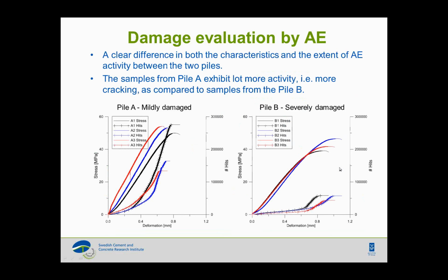This is just some results from acoustic emission for pile A and pile B. That's why we were actually putting these piles in compression, and what we saw was that we had a lot more fracture activity going on for pile A. The reason was that it was not damaged, so we had to develop the cracks while we were putting that under mechanical loading. While in the severely damaged case, many cracks had developed before, so there was less fracture activity going on, but it was more about opening up the existing cracks.